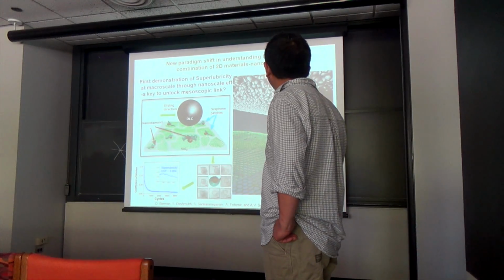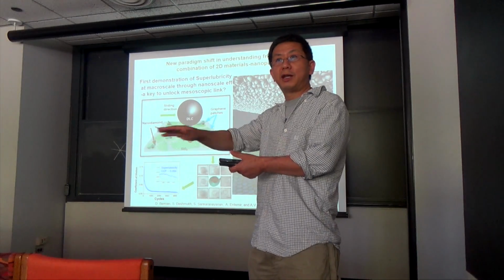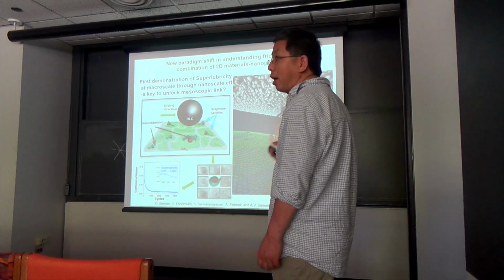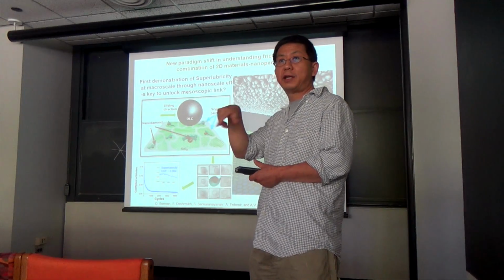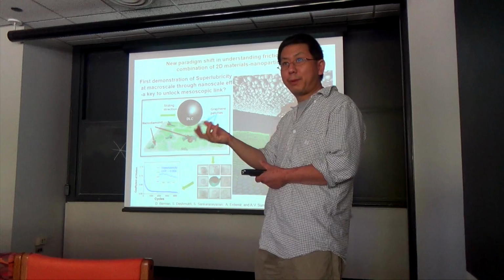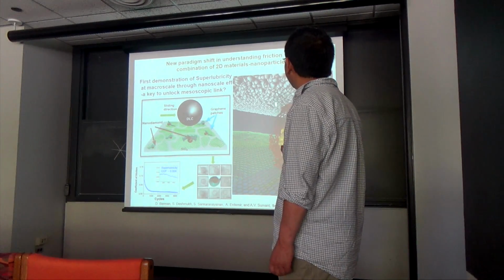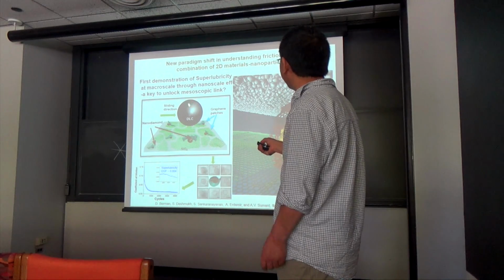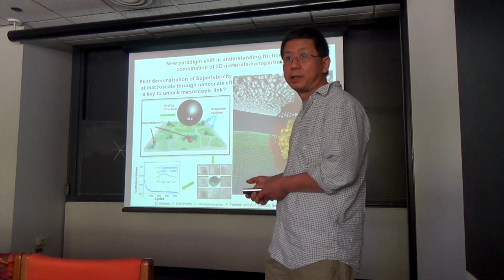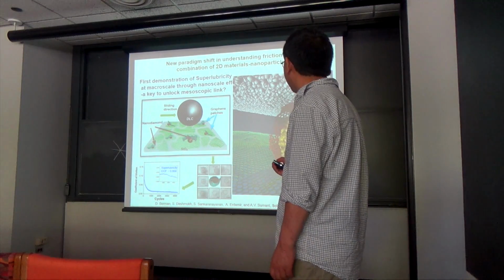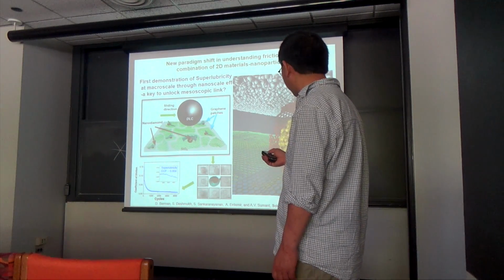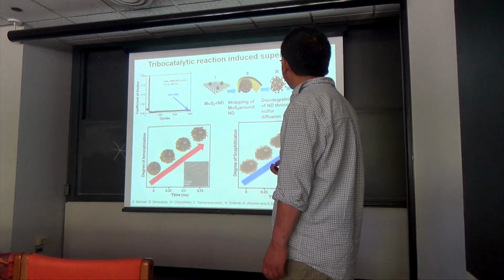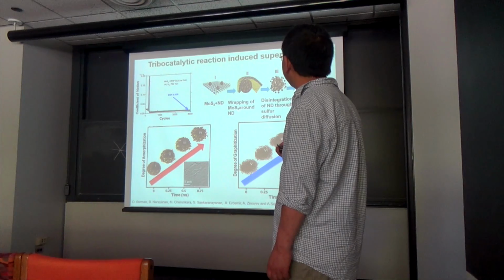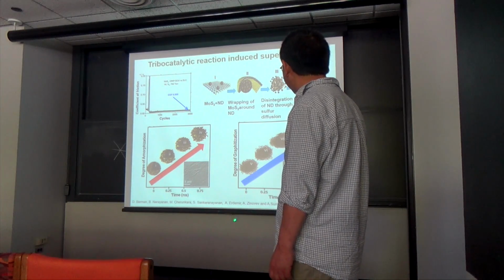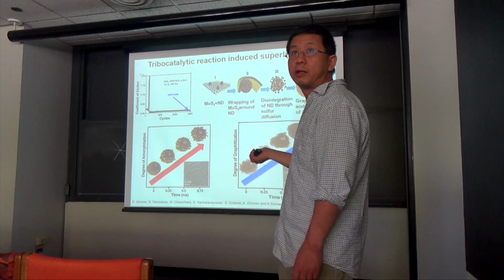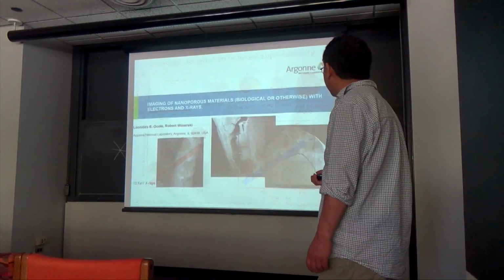They tried to understand exactly what happens. Eventually they realized that when you slide material on this kind of system, you are essentially wrapping graphene layers around the nanodiamond particles. Once that happens, it decreases the friction force between the ball you are trying to push and the surface dramatically. That's an interesting effect on its own, and it was published in Science in 2015. They did simulations of these mechanisms and found out exactly what happens in these types of systems. These are all done at Argonne with simulation effort.